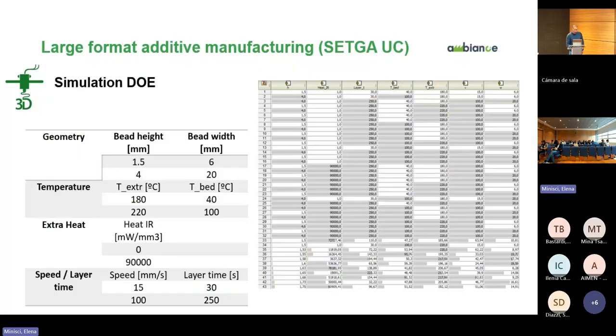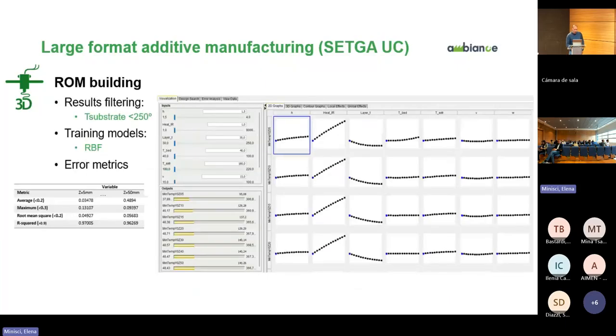Again, we generate a DOE. In this case, it was a larger DOE. We managed with 7 parameters, combining geometry dimensions, temperatures of the extruder, temperatures of the bed, the infrared heating, speed, and layer time. So again, we built the ROM, and we have one model that gives us results for different layers and heights, and also we have the possibility to obtain different points of the temperature, different points of the bead, in the center or in the side. And more or less, this will cover the full simulation models for the set values case.